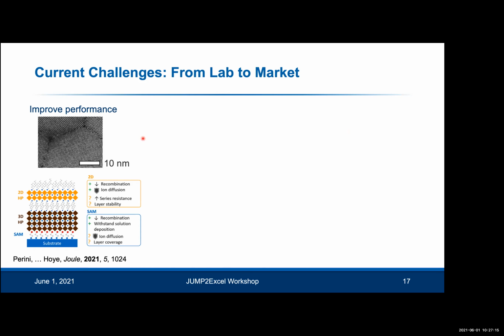with the efficiencies. And that includes being able to look at this material at the atomic level. So what you're seeing here is a high resolution transmission electron microscopy image of this material, formamidinium lead iodide perovskite. And this used to be quite challenging, because it used to be that if you put the perovskites under a high energy electron beam, it used to just burn the material.